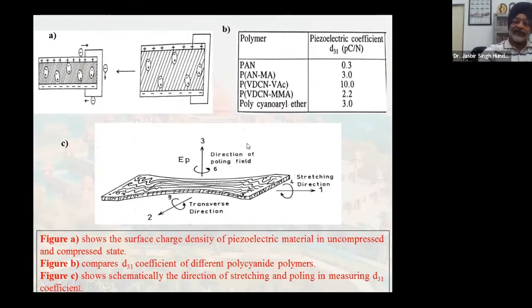Then we can have even D33. In that, we measure the charges on the same face, and whatever needs to be deposited on top, we deposit on the same surface. But when we are measuring D31, the sample is cut in such a way that the film is stretched in this direction, and the change of charge is measured along the 3 direction.